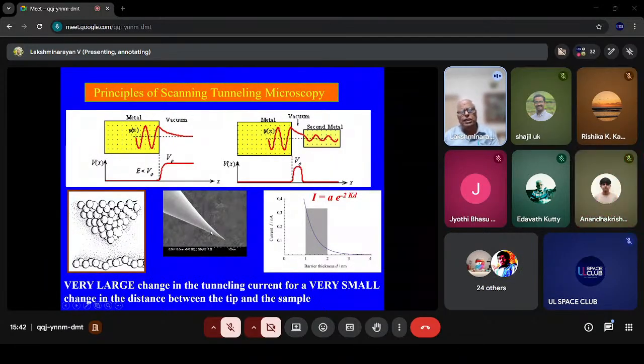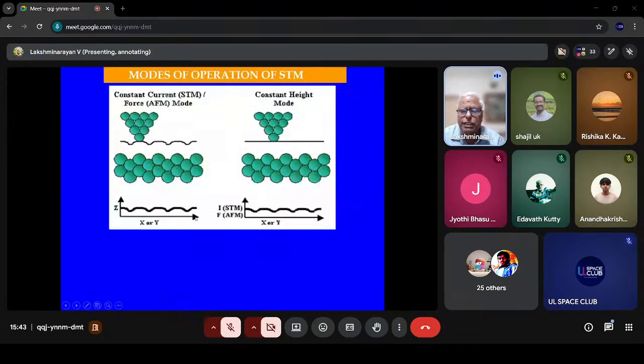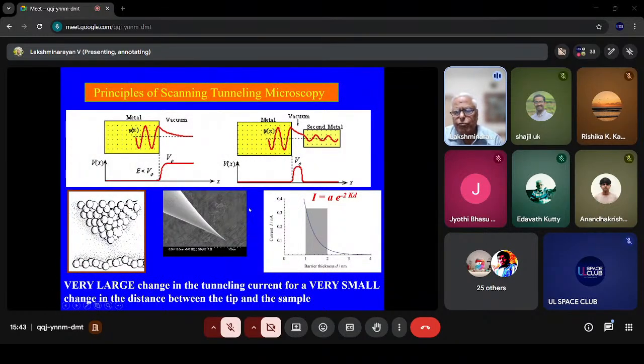So all that one needs is a very, very sharp tip like this. This tip has to be very rigid. So it can be something like tungsten, which is my favorite one, because it's very rigid, and you can't really easily bend it. It's not ductile like platinum, iridium. Platinum-rhodium is also used, but it's more ductile. So this is the kind of tip you can actually use. And when you scan this tip over a surface, you will find the gap distance between the sample and tip changes as the tip hovers over the surface.